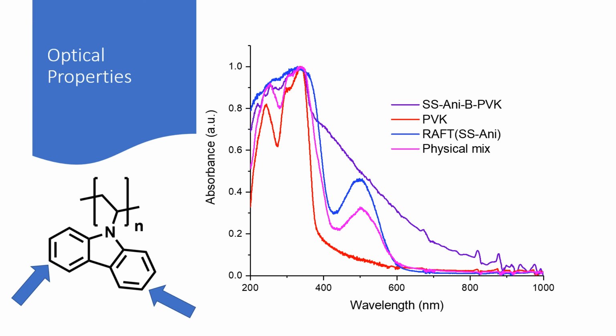Optical properties. The optical properties of the polymer were studied through UV-Vis spectroscopy. We can observe that conventional polyvinyl carbazole only absorbs in the UV region. Also, the macro-RAFT agent, which is in blue color, absorbs in the UV region and in a short part of the visible region. The physical mix of both doesn't present absorption in other regions than these. On the other hand, the block copolymer presents absorption in the UV region and a wide range of the visible region.